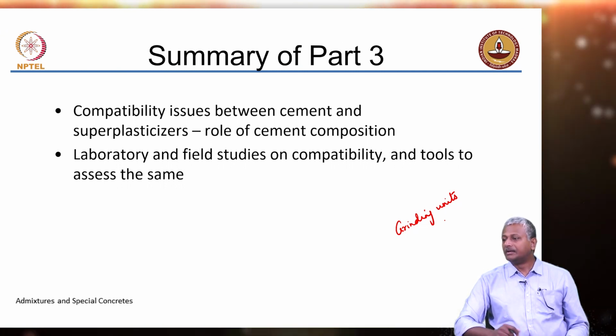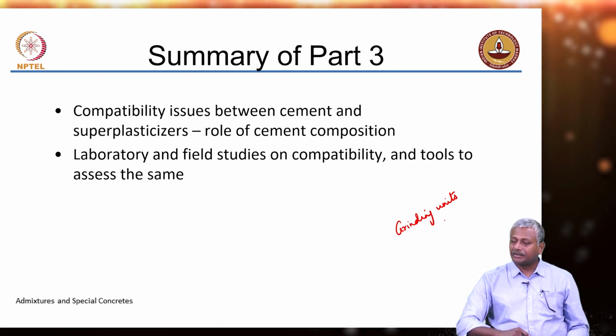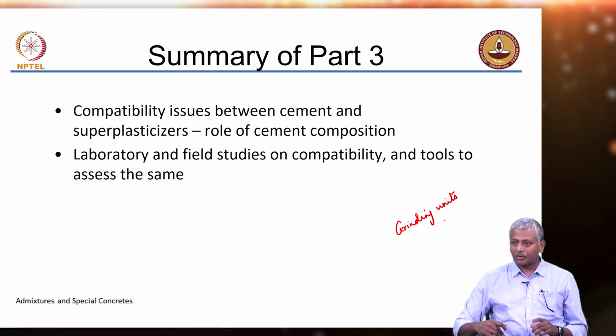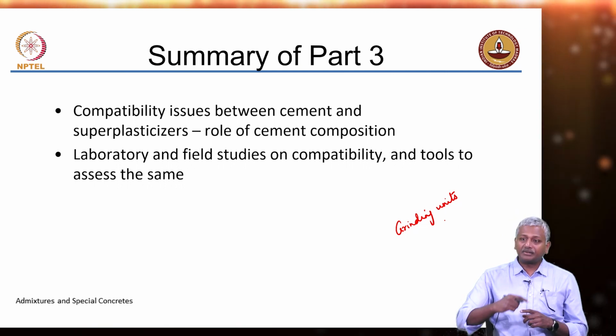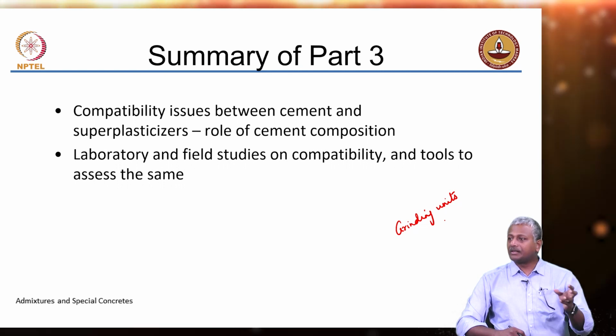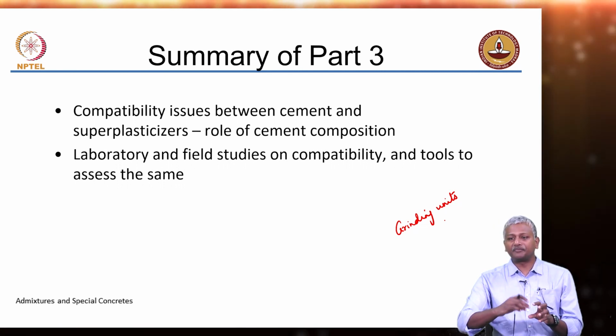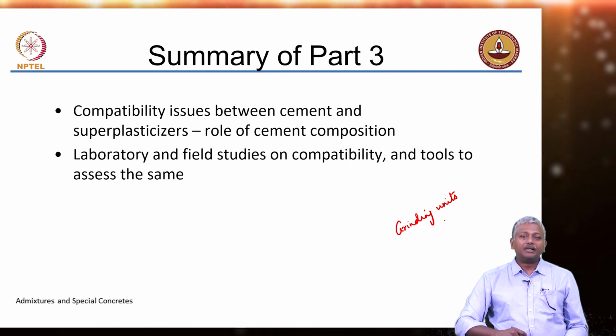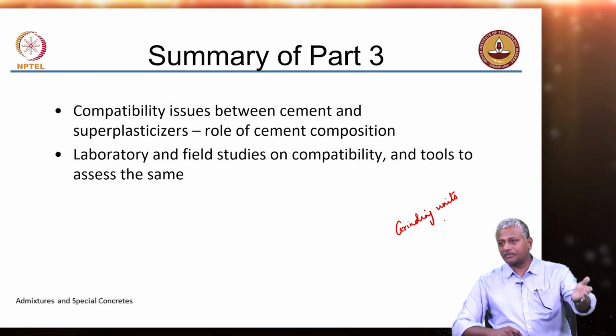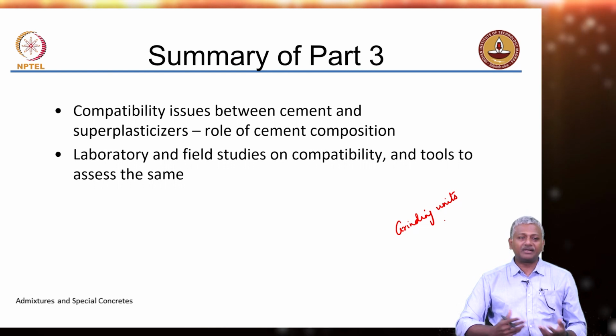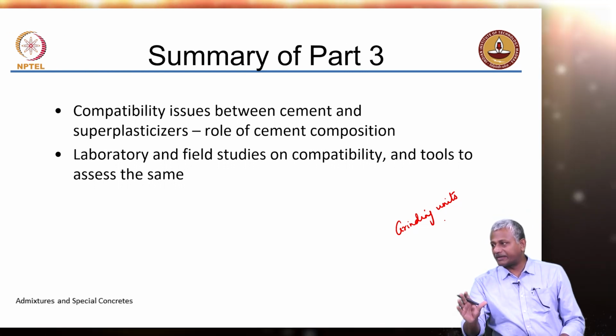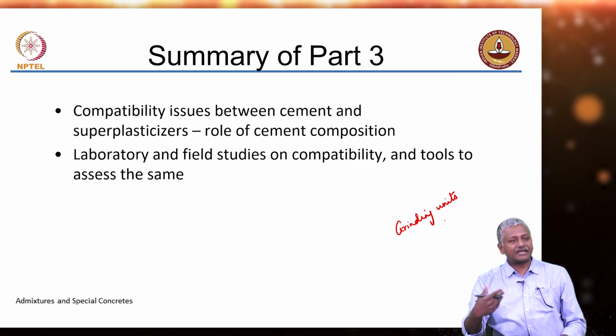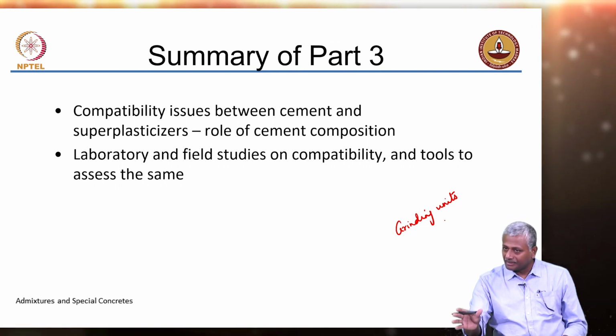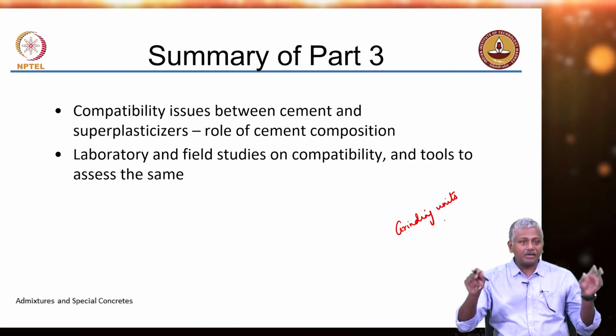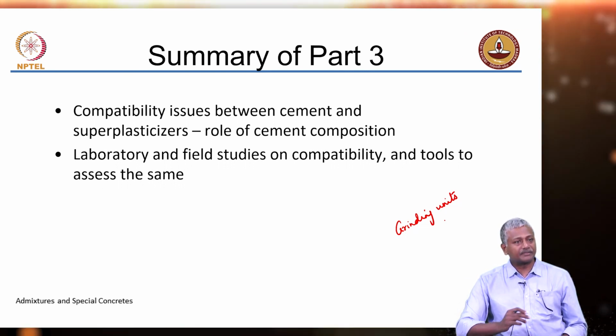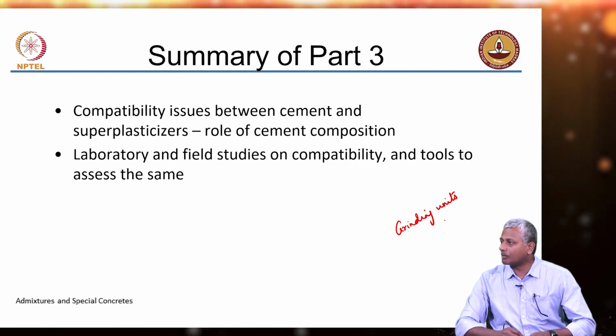So, for instance, there are several grinding units in the northern part of Tamil Nadu where they get clinker either from the Ariyalur belt, which is about 250 kilometers south of here, or from the Tadipatri belt, which is in Andhra, right. So, the clinker obviously depends on the characteristics of the limestone that is available in these two locations. It turns out that when you make cement with the clinker obtained from Tadipatri or from Ariyalur, it actually ends up giving you a very different characteristic. The cement ultimately has to meet the specs, right. It has to meet, let us say if it is a 53 grade cement, the required setting time, required strength, all of those things are fine, but the same brand of cement can behave quite differently when you use admixtures because of all the problems that we talked about previously.